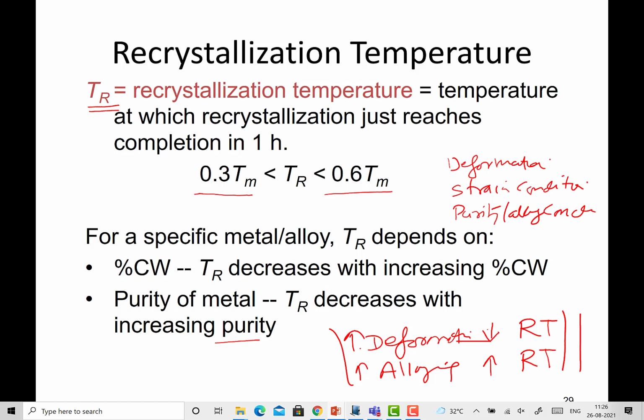Why am I talking about this here? Because you know, in your solid state joining, either the interfaces are deformed or the weld nugget is deformed. So the weld nugget will be experiencing a reduced recrystallization temperature. And so even with a little heat, there is a possibility of recrystallization of the metal or formation of new grains.